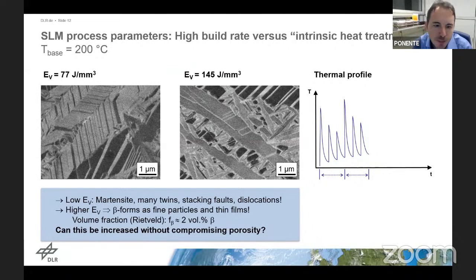These images show some SEM images of the as-built microstructures that we get from the process run at 200-degree base plate temperatures. On the left-hand side for titanium 6-4, the very typical martensitic structure that you get due to the very high cooling rates of the process. The SEM shows a lot of lattice defects here, especially twinning in the material, dislocations that I will come back to later.